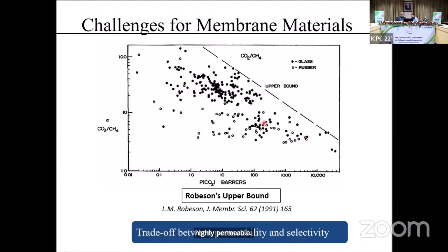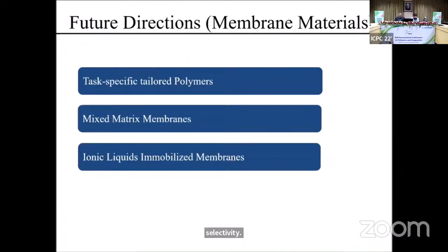And he said that in order to commercialize the membrane, in order to take over from adsorption and competing technologies, we have to develop membranes that show performance in the region above this negative slope line, which he called the upper bound. So a material that can be commercialized for membrane-based gas separation should be one that shows simultaneously high selectivity and high permeability. So this is the target region for membrane researchers.